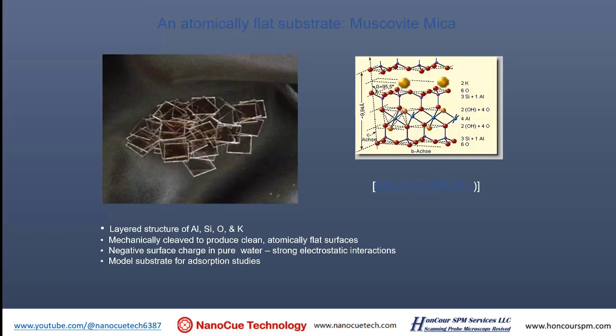Several characteristics that I need to mention to you about this mica. One is that mica surface is actually negatively charged. The surface has negative charge in pure water. But you can turn it into positive charge. Later I will mention how to turn the surface into positive charge. So it's a flat surface, hydrophilic, and negatively charged. The only problem of mica surface is it's not conductive, so you cannot do STM on it.